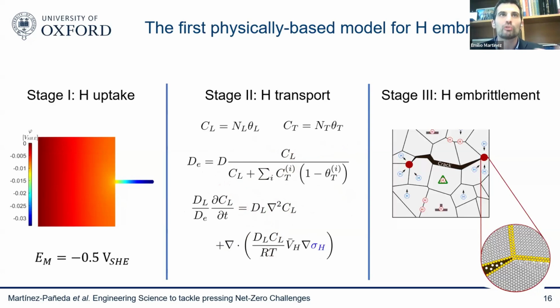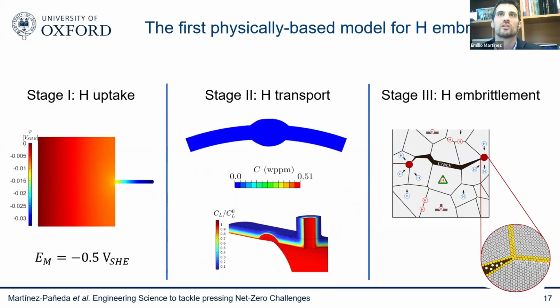So again, by applying brute force, we finally have computer models that are big enough. We can solve all these interdisciplinary problems at the same time. And by the way, all of this, the coupling is quite strong. All of these phenomena are quite coupled. So this is a hydrostatic stress. So the deformation of your material is going to drive hydrogen concentration. So that's quite important. So it's a coupled problem, but if you can do clever experiments to resolve those couplings, then you can solve with computers all the equations that are describing those physical processes.